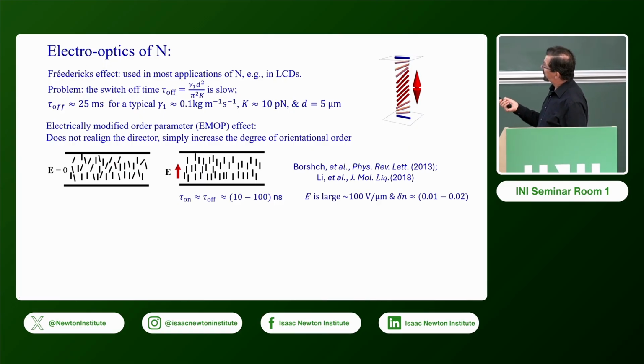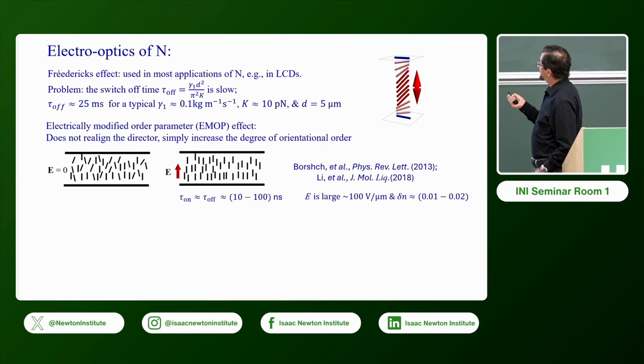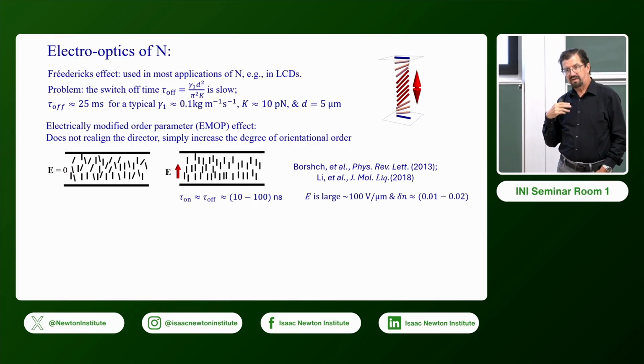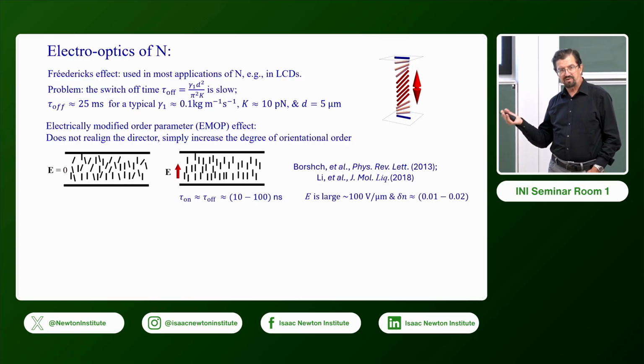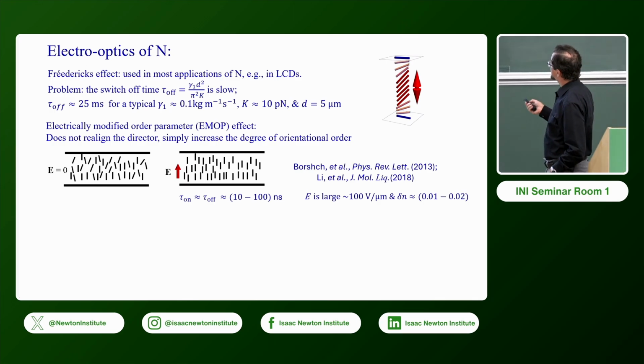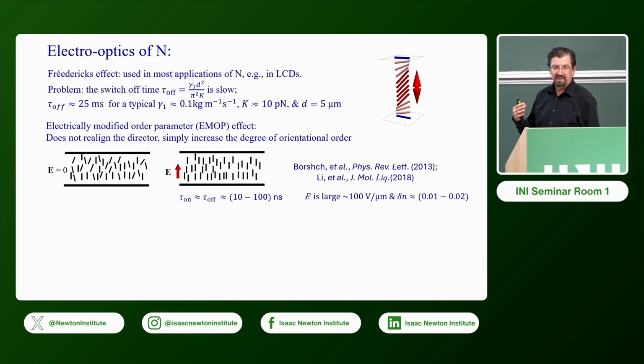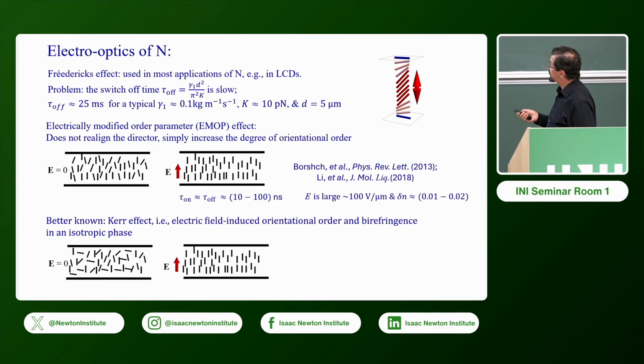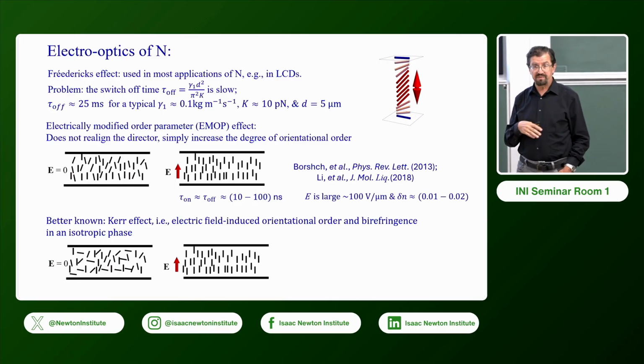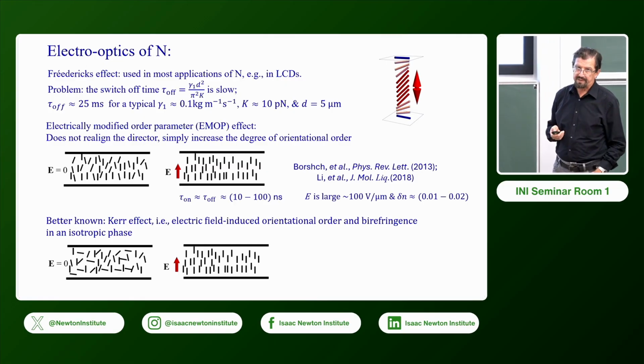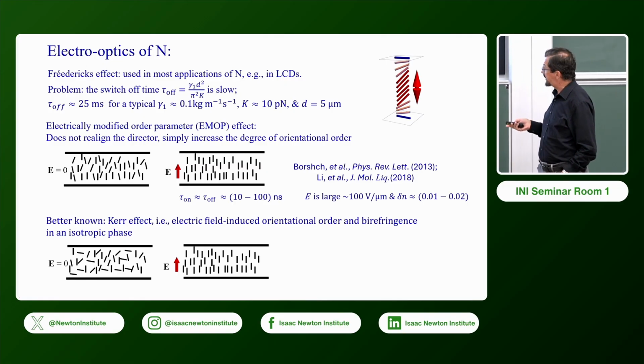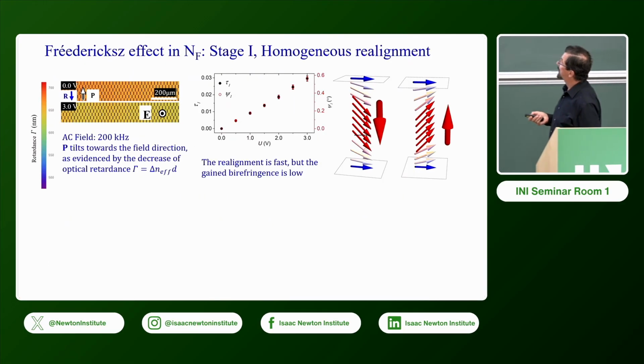But the problem is that in a normal nematic, the change of the birefringence that is induced by the field is relatively weak. It's about 20 times lower than the natural birefringence of the material. And so another very closely related effect to the one that I described here is the Kerr effect. You start with an isotropic fluid, you apply an electric field, it transforms into the nematic, and that is also a possibility, but the numbers would be approximately the same.